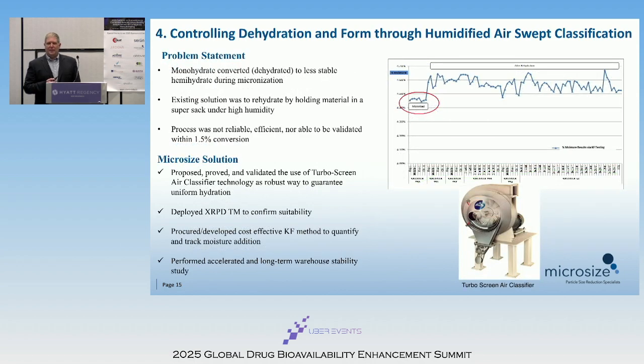And then finally, this is our controlled dehydration through humid air swept classification, which we use a turbo screen, where we converted a monohydrate to a hemihydrate during the micronization. It dried out, and we were able to essentially rehydrate that material by humidifying the air in the room and then running it through a turbo screen, so each individual particle is exposed to moisture. And the existing solution before this was to just hang material in a super sack for a week, but it wasn't reproducible because moisture wasn't migrating into the super sack. With turbo screening, each particle gets exposed.